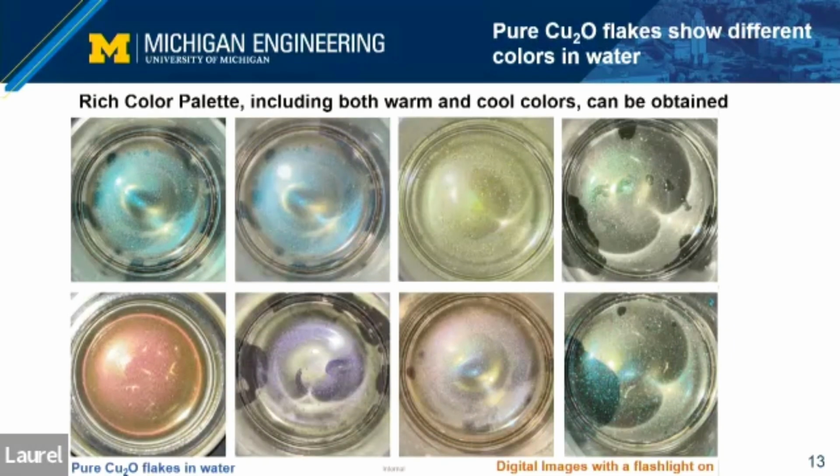For the size, it is very hard to control, I have to admit, because it depends on the time and also on what kind of sonicator you are using. So it depends on your experience, and you can create different kinds of appearances for these pigments. We are also trying other ways, like using annealing to peel them off the substrate, and that might provide better control on the thickness and size of the pigments. It might be very small if you sonicate for too long. That's a good question. Thank you.